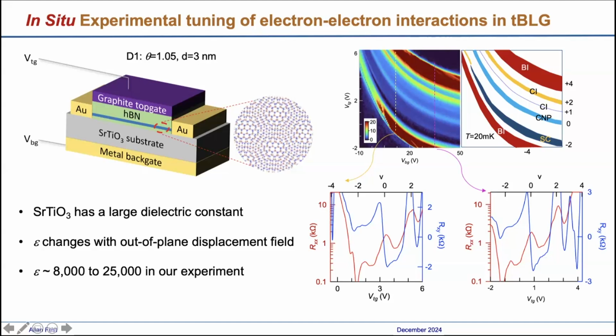Here we're plotting the resistance as a function of top gate voltage and back gate voltage. This very resistive red state is the band insulator. This is +4, this is -4: 4 electrons or 4 holes per moiré unit cell. This is the charge neutrality point, a global charge neutrality point. This is the correlated insulating state at +2, and this really dark region is basically superconductivity.